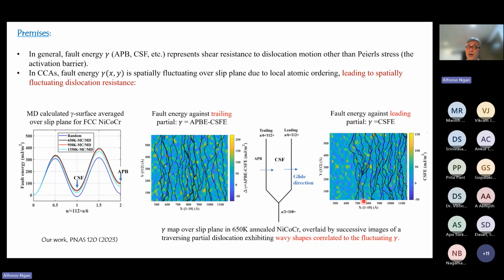As you can see, this is the slip plane, and the fault energy is not a constant value. It fluctuates spatially. And overlaid on top of this profile, the black lines are images of one partial gliding through the slip plane from the left to the right. So you can see that the dislocation is always wiggling as it glides through this fluctuating gamma landscape. Obviously, this is due to the interaction between the dislocation and the solute atmosphere in the slip plane, which is represented by the fluctuating gamma.